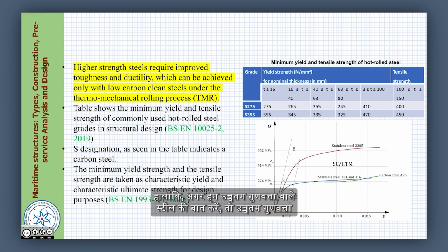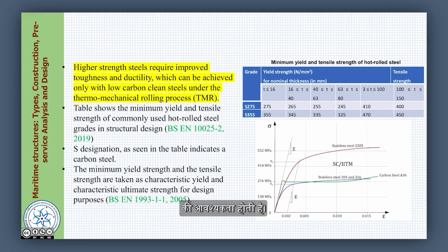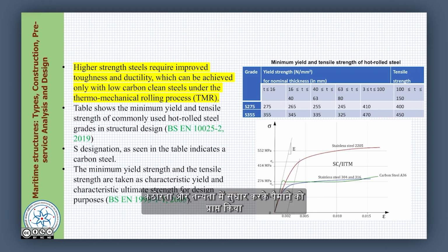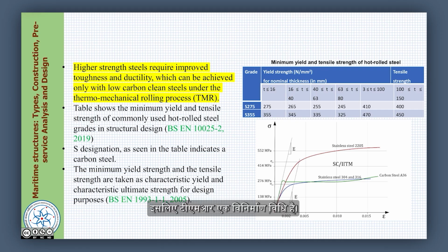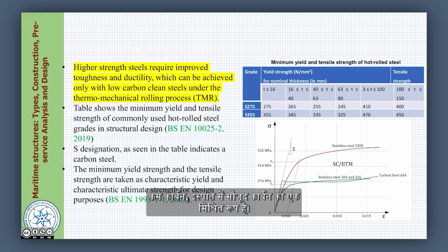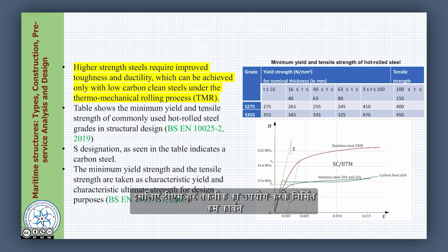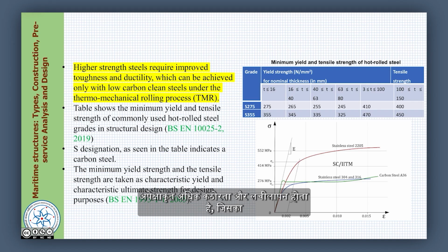If you look at higher strength steel, though higher strength steel can reduce the volume, you need to have enough toughness and strength. For this, higher strength steel can be achieved by toughness and ductility improvement, and they can be achieved by low carbon steel manufactured using thermomechanical rolling process. So, TMR is a manufacturing method, low carbon is a composition of carbon in steel. So, low carbon steel manufactured using TMR technique can arrive to be high strength steel, which has relatively higher toughness and ductility, which is commonly used in maritime structures.